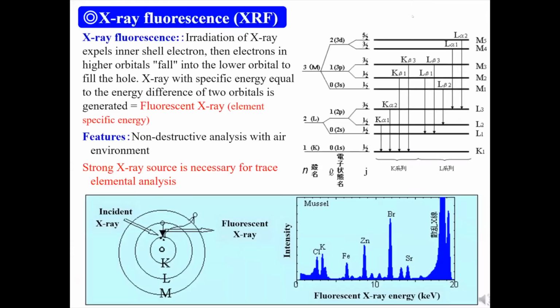We applied synchrotron radiation X-ray fluorescence for the analysis of trace elements in biological tissues. As microscopic elemental analysis, SEM-EDS is one of the most popular methods. X-ray fluorescence, XRF, is a similar method to SEM-EDS. A high-energy X-ray is the excitation source of XRF, and characteristic fluorescent X-rays are emitted from the irradiated elements. The energy of characteristic X-rays is element-specific, so elemental analysis can be carried out by XRF. In addition, X-ray irradiation seldom damages the specimens. Then, XRF is a non-destructive analysis.